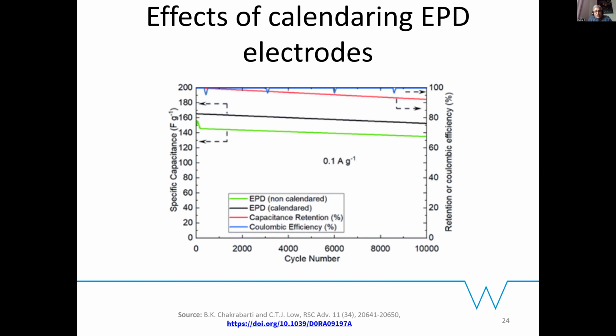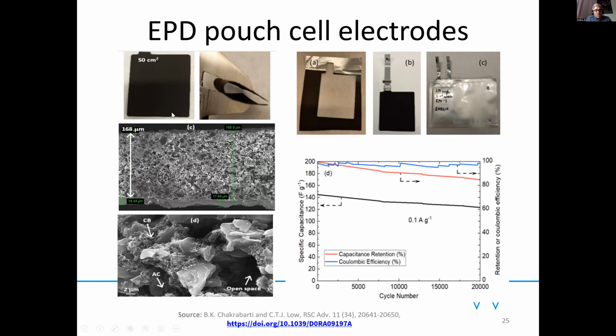The challenges we faced when scaling up were obviously because the reactor for the electrophoresis would have to be bigger. Maintaining the same amount of colloidal suspension as for a smaller bath is more challenging, so we need a larger sonication reactor, and the sonication time is longer for the larger reactor to maintain the same amount of colloidal suspension in the solution for larger electrodes. The temperature and the stirring rate for the electrophoresis had to be taken into account to make electrodes for pouch cells. So here are the electrodes that we prepared for pouch cell studies.